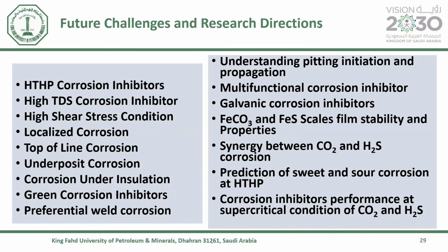This is an area that is still very challenging to mitigate using corrosion inhibitors. Then under-deposit corrosion, where you have scale formation and then corrosion with scale. This is very challenging. Corrosion under insulation and green corrosion inhibitors. Normally green corrosion inhibitors sometimes work at low temperature, but the challenge would be developing green corrosion inhibitors for high temperature and high pressure conditions. Preferential weld corrosion inhibitors are very scarce, and there is corrosion at these preferential welds. This is one area that is very important to look at.